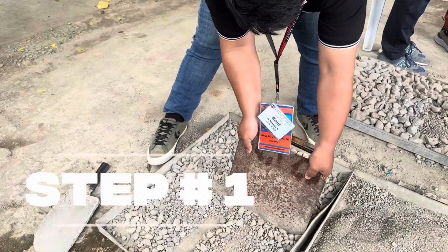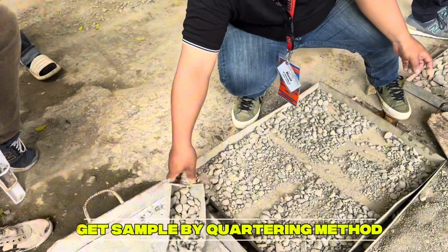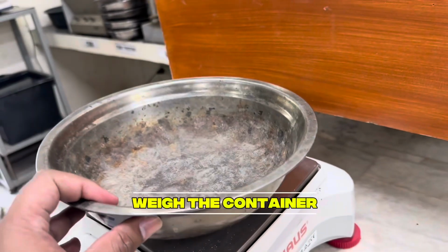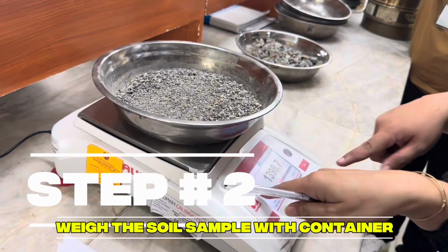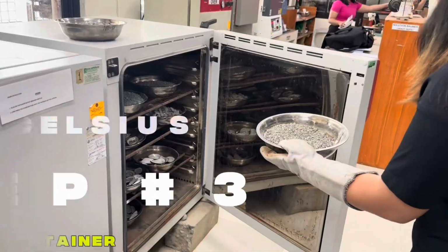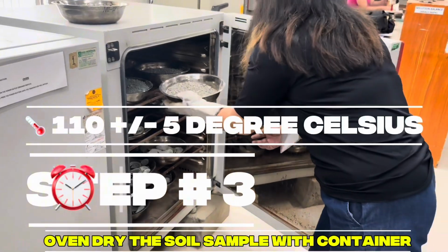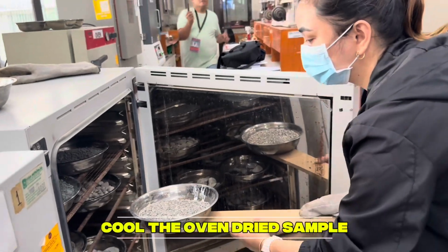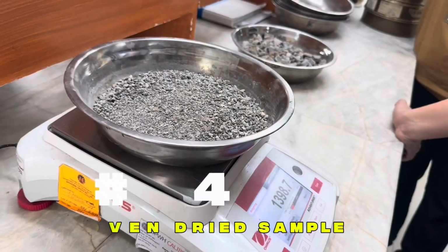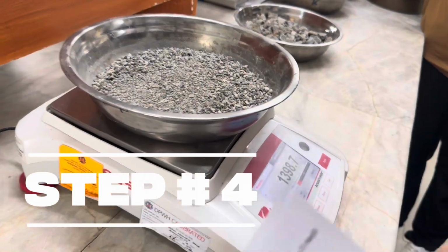So here's the simplified procedure. We begin with step number 1. We get samples by conducting a quartering method and also weigh the container to be used. Step 2, weigh the soil sample with the container. Step 3, oven dry the sample for 2 to 4 hours. Then cool the oven dried sample. Then step 4, weigh the oven dried sample.